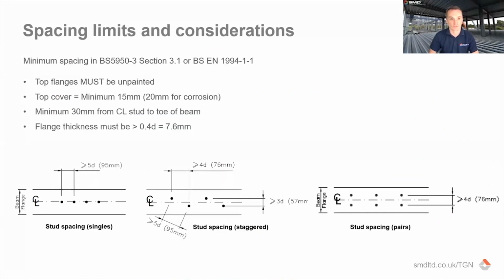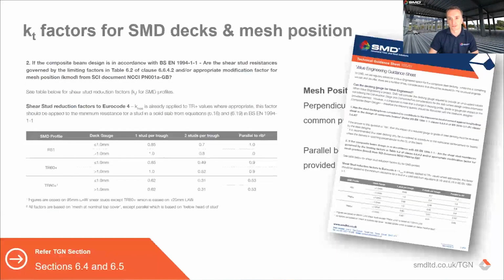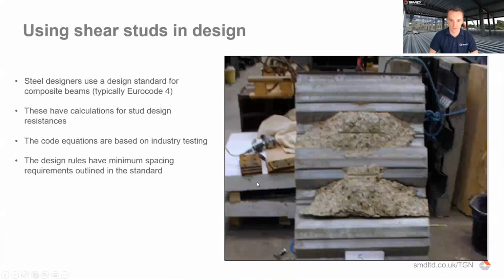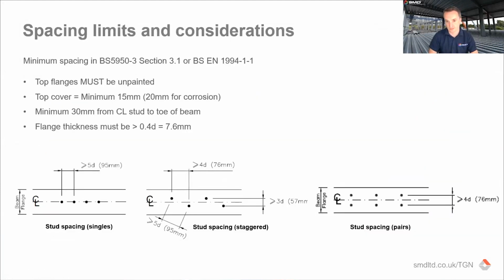If you up the grade of concrete, obviously your shear surface area is the same, but the resistance within that shear surface is higher because of the higher concrete class. So you could up the concrete class, or a thicker deck would give you a greater KT factor. And that is why in this sheet I show on the right here, we give this value engineering guidance sheet out, because if someone is trying to value engineer from a 1.2 to a 0.9, let's say, if they've utilized 1.2 and that's quite important in the shear stud resistance, then a 0.9 may not work. That's what this sheet is all about. But the answer to the question would be yes, upping the concrete or the deck thickness will increase, although not massively, the stud resistances. I hope that answered that.